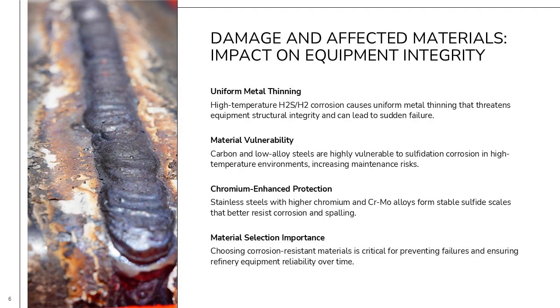High-temperature H₂S or H₂ corrosion primarily causes uniform metal thinning, which can compromise the structural integrity of critical equipment. This type of damage is particularly dangerous because it may not produce visible signs until significant metal loss has occurred, increasing the risk of sudden equipment rupture. Carbon steels and low-alloy steels are highly vulnerable to sulfidation, while stainless steels with higher chromium content, such as 304H, 310, and CrMo alloys like P91, exhibit better resistance. Chromium enhances the formation of stable sulfide scales that are less prone to spalling, providing improved protection against corrosion. Selecting appropriate materials for high-temperature environments is essential to prevent catastrophic failures and ensure long-term reliability of refinery operations.